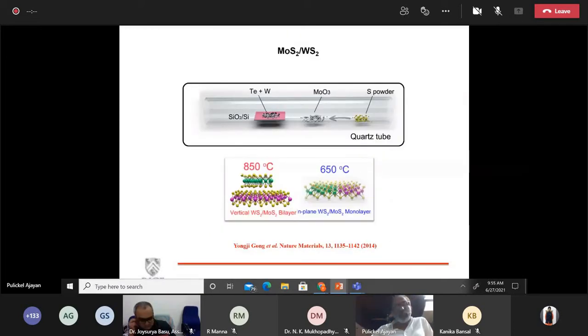One way to do this is using multiple precursors and using vapor phase deposition. And we have grown many of these hybrid layers together, and they can be formed. For example, molybdenum sulfide and tungsten sulfide are very similar types of material. And using different precursors, you can create these heterostacks. Now, it looks like you can optimize windows in which you can grow these stacked structures that are completely segregated in composition. Or in many cases, what happens is that within the same layer, you have a contiguous structure with different domains of tungsten sulfide and molybdenum sulfide and these domain boundaries. So you can have these in-plane structures as well because they are isostructural.